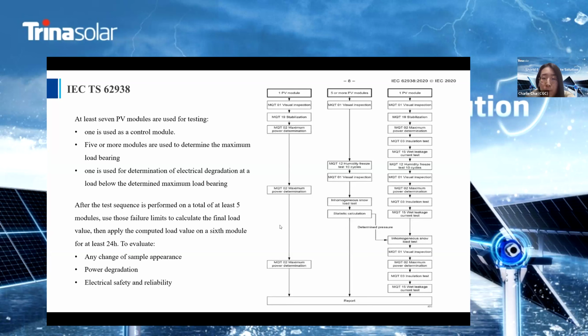After the test sequence is performed on a total of at least 5 modules, use those failure limits to calculate the final load value. Then apply the computed safety load value on a 6th module for at least 24 hours to evaluate any change of sample appearance, power degradation, and electrical safety and reliability. Less than 5% power degradation, no visual and electrical failures means the module passed this test.